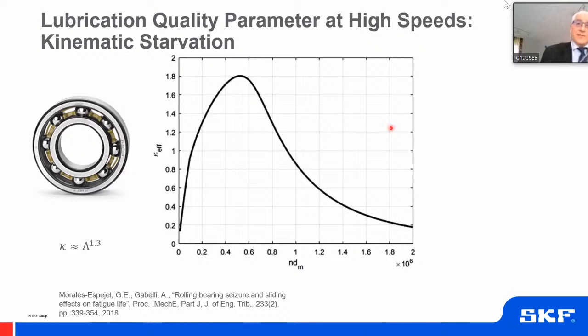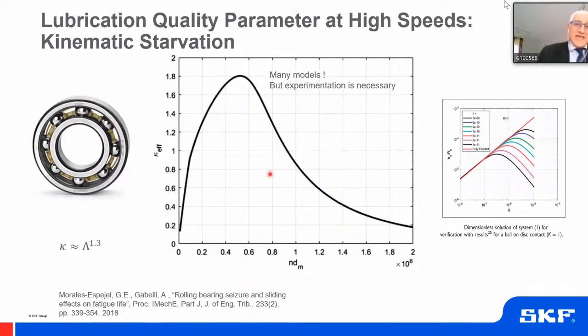Now, there are many models to capture this. But eventually we have concluded that at the end of the day, you need some experimentation, because it's extremely difficult to model in advance what are the conditions of the lubricant just in front of the contact. If you manage to do that, then you can model everything, and we can do that in the laboratory, but not in a real machine element. This is an example of what is possible to do in the laboratory in a tribometer consisting of a disc and a ball. You can pretty much model the conditions when you increase the speed. You can model all starvation conditions if you are clever enough, in a very controlled way.